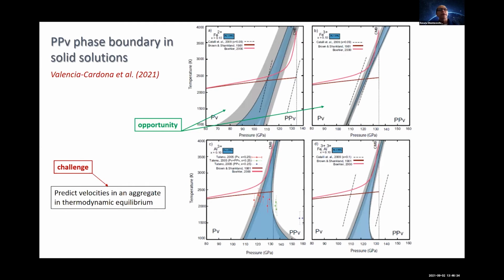Because today we investigate the same phase transition in alloys: bridgmanite with ferrous iron, with ferric iron, or just aluminum coupled substitution, or aluminum and iron at the same time. And what we see, as in experiments, is that ferrous iron decreases the transition pressure, but also opens a two-phase stability field. Ferric iron pushes a little higher the transition pressure and has a quite narrow two-phase region. So is aluminum, the aluminum-bearing phase at the conditions of the mantle, and the iron-aluminum coupled substitution.